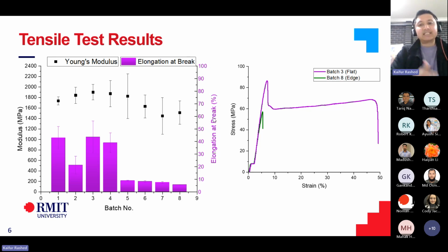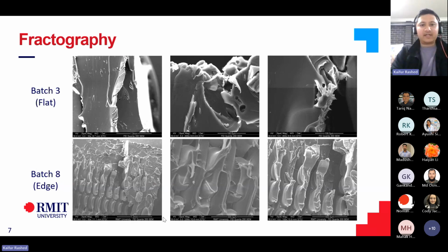Part of the research was understanding why this happens. So I performed some fractography analysis. I took the failed samples and examined the cross section of the failure. Sorry, I'm losing words here. I looked at the cross section under an SEM, and you can see clearly in batch 3, which is the flat sample, the failure was mostly ductile, but in batch 8, you can see the individual rasters, and you can see how it failed in a brittle manner.